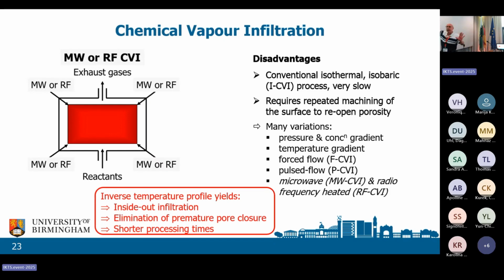Many people have looked into how can you speed up the process: pressure and concentration gradients, temperature gradients, forced flow, pulse flow. None that I'm aware of are now commercial. At Birmingham, and before I was at Birmingham, we looked at microwaves for silicon carbide fiber preforms. Silicon carbide fibers absorb microwaves very readily. And for carbon fiber preforms, we use radio frequency, RF. Again, carbon fibers absorb it very easily.